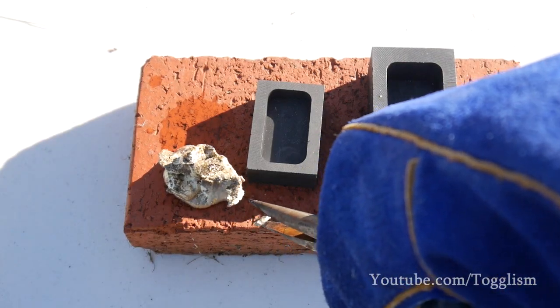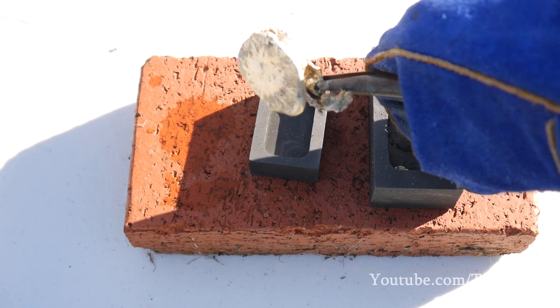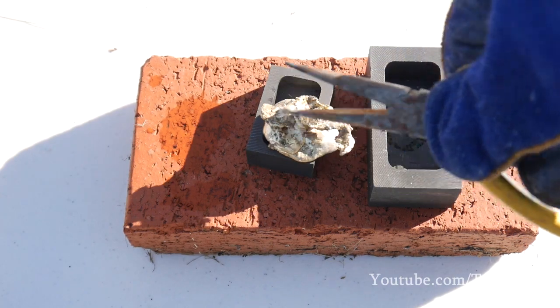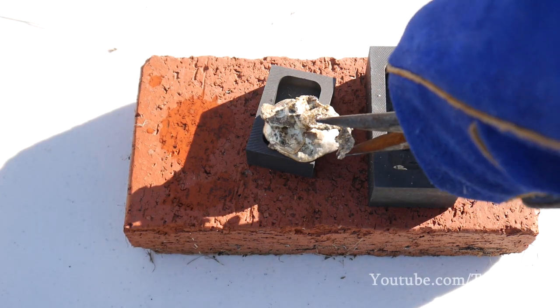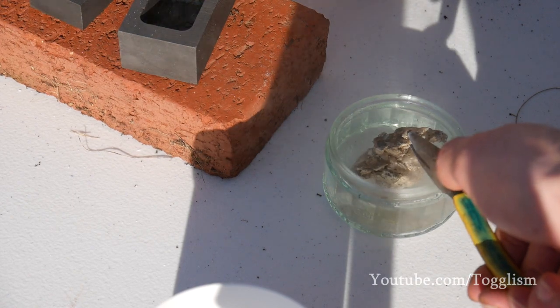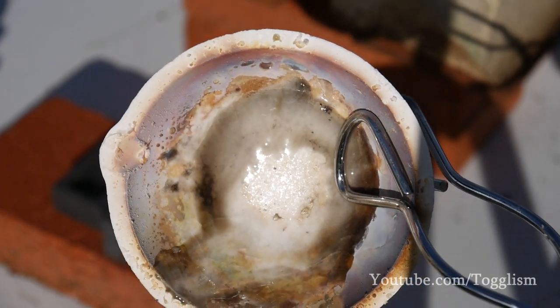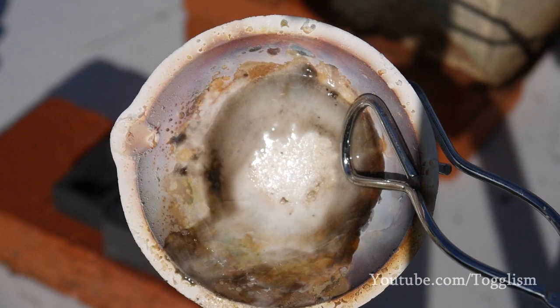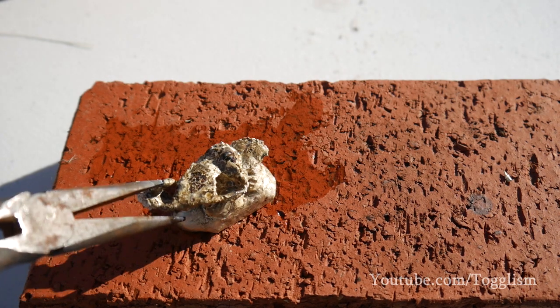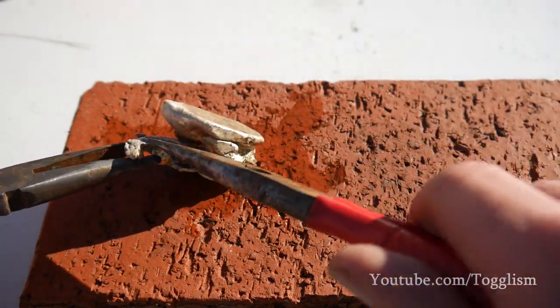It was quite difficult to keep the silver molten as I moved it to be poured into the mould, and also I think the mould wasn't quite hot enough — something to remember for the future. As you can see there's a big lump of slag on the top of the silver. This would most likely be the nickel from the biker rings which rose to the top as nickel is less dense than silver. It's a beautiful bit of silver underneath, and interestingly the borax glass in the crucible started making a clinking sound as the glass rapidly cools and cracks. There we have it — the world's most dodgily cast bit of silver, along with a big nice lump of slag on top.